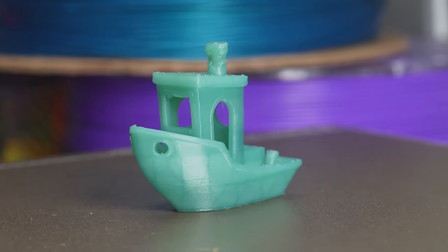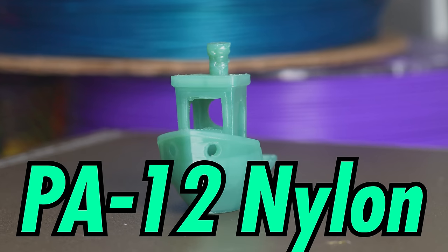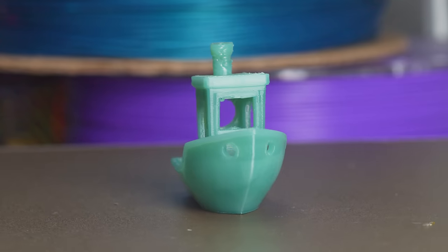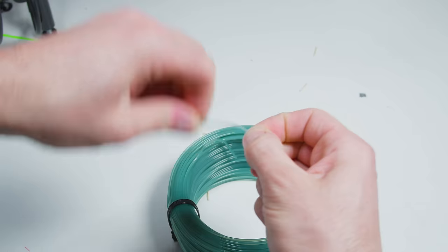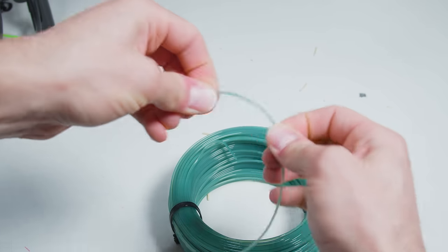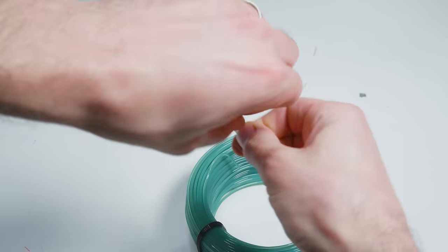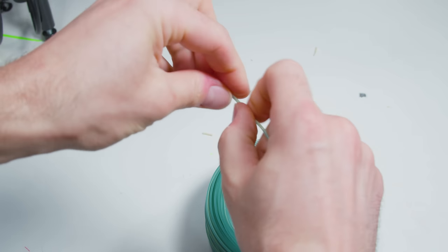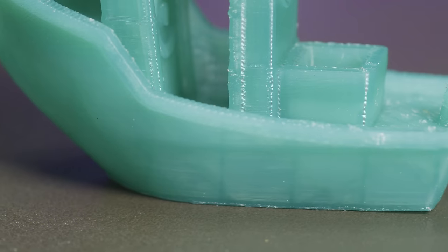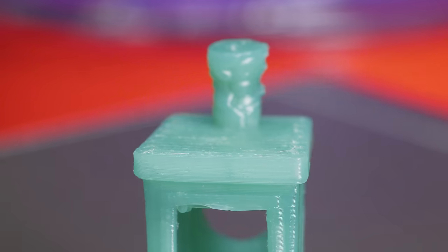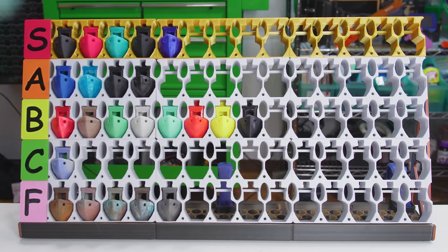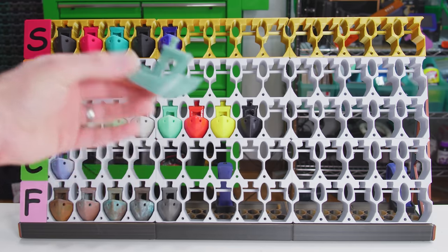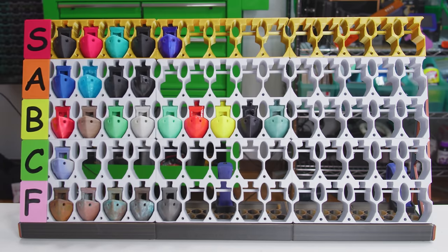But sometimes, you really need to crank the heat. You want PA12 nylon. This stuff prints way hotter, usually around 300 Celsius. And since it warps even harder than PA6, a hotbox is an absolute requirement. PA12 is stiffer than PA6, so it's better for cars, RC vehicles, machine tools, and other heavy-duty but precision jobs. Remember, rigid means brittle, so as durable as PA12 is, it's still easier to break than PA6. I'm gonna put PA12 in B tier. It's got advantages over PA6, but since it's more expensive and harder to print, you're usually better off with its less carbonated cousin.